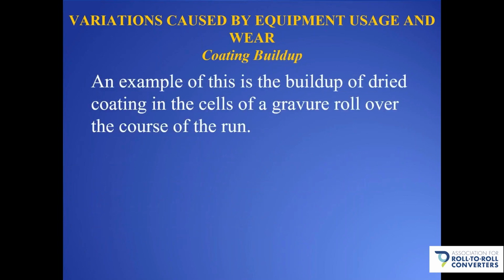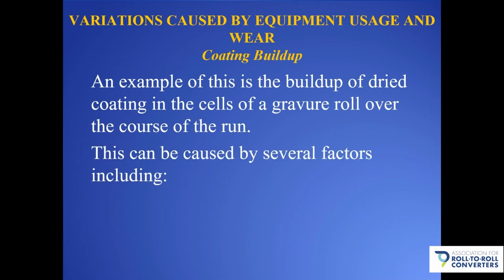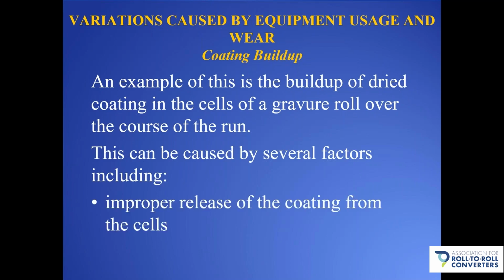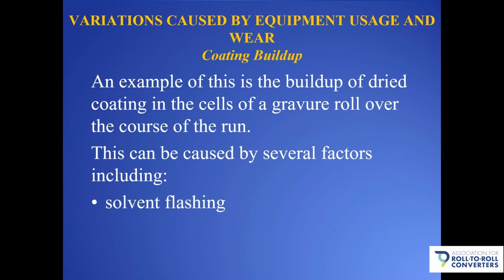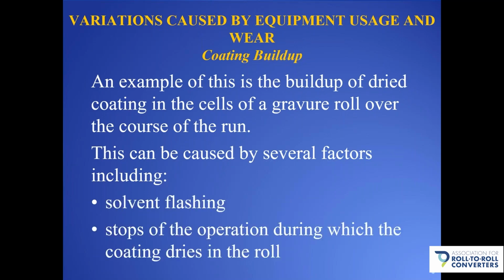Now, a specific example of this is buildup of dried coating in the cells of a gravure roll over the course of a run. And this can be caused by several factors, including improper release of coating from the cells, poor doctoring of the roll, solvent flashing, and stops of the operation during which the coating dries in the roll.